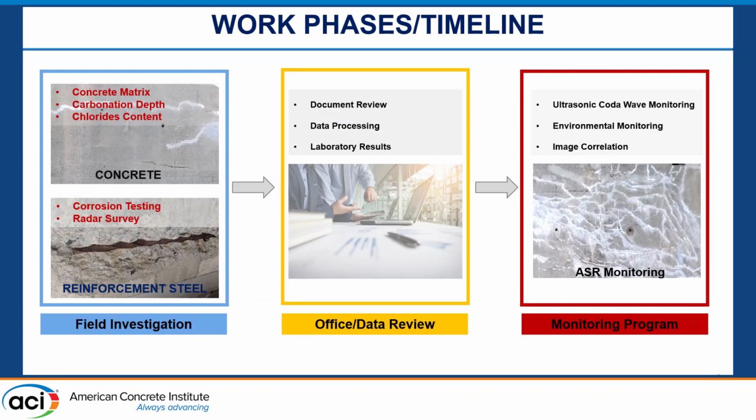Like all good studies, we had to break down and understand what the mix of the concrete was and where the problems were coming from: chlorides, carbonation depths, all the typical NDT type work you would do on a structure. Then we developed a monitoring program using techniques that maybe hadn't been used before. Some strain gauges had been installed, but the way the structure was moving, they were not giving us much; they were just monitoring the crack in one direction and not linearly along its length.